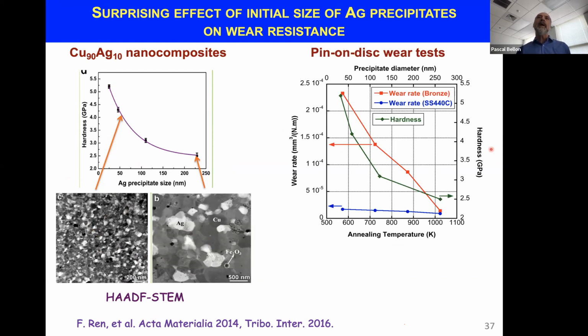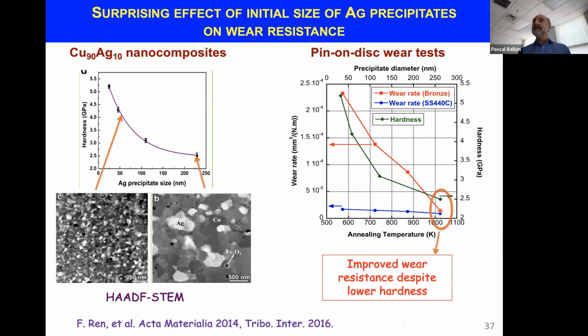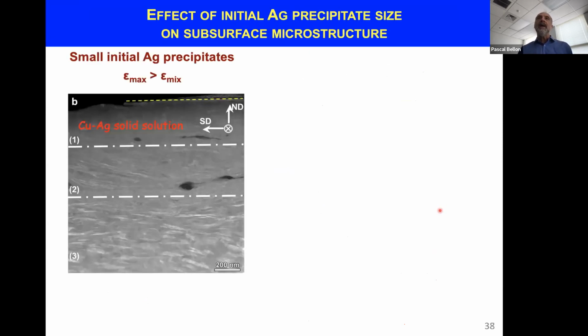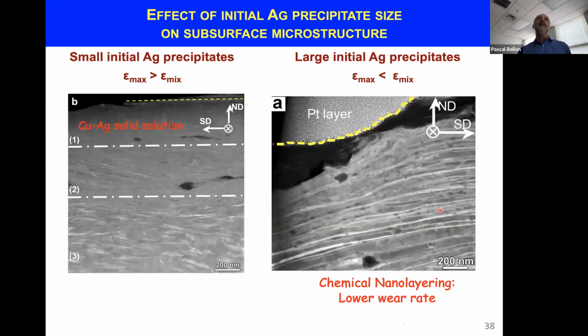And we found that the wear rate, which is the blue or the red curves reported on the left-hand side, is lowest when the hardness is the lowest. And these are the points on the right. This is kind of surprising, that low hardness would improve wear resistance. And when we look at the microstructure of these materials, what we found, and that's what you see on the right-hand side, is that the material that has a high wear resistance is one where spontaneously the copper and silver phases form a nano-layered structure.